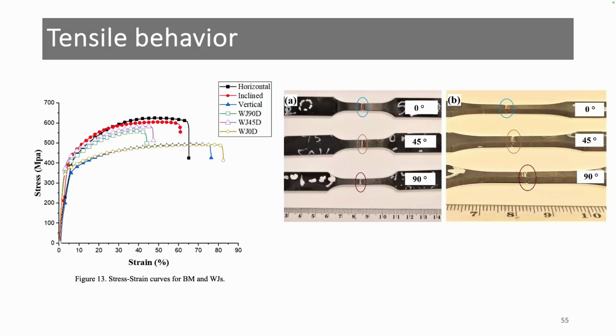And when we compare the fracture location of the weld joints, we will find that for the 90 and for 45, the fracture happened at the fusion zone. It means that there was some softening here in the fusion zone compared to the base metal. While in the 0 degree, the fracture happened outside the fusion zone, was in the base metal. And this is normal because there's very similar behavior for the stress strain curve.